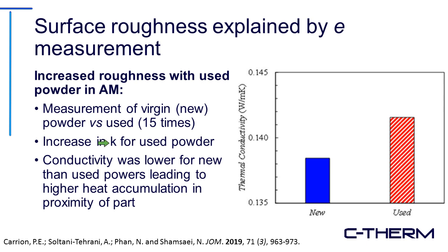And the way that they explain this is by looking at the thermal conductivity, which was measured using our MTPS sensor. They were able to calculate the thermal conductivity of new versus used powders, and found that there is an increasing tendency for the thermal conductivity to go up with more used powders. And this was important because thermal conductivity, if it's lower than used powders, will lead to higher heat accumulation in the proximity of the part, which will increase the surface roughness of the part which is being manufactured.